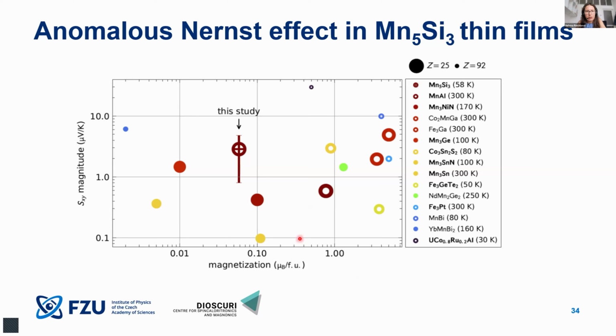And we can see that Mn5Si3 is already pretty comparable to many materials, where the highest value is naturally achieved in this great work, relying on a heavy element. I try to highlight the atomic mass by the marker size. And yes, these are indeed unbeatable to some extent. However, coming to more abundant compounds such as cobalt, manganese, gallium, we see that we are already in the same range, despite having a metallic thin film with manganese and silicon, which are all light elements.